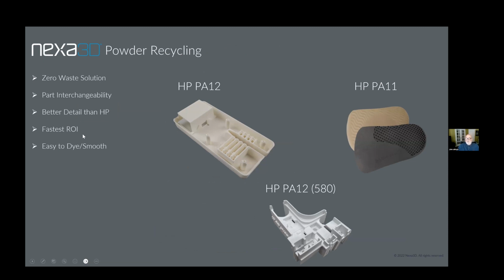That's one of the questions I get most: yeah, you can recycle, but are the parts good? Actually, the parts are outstanding. What we found through mechanical testing and from time in the field is that we have complete part interchangeability, which means the parts printed on the QLS with the HP MJF waste powder are equally as good in every aspect as the original HP parts printed with virgin material. The only difference you're going to see is a little discoloration.